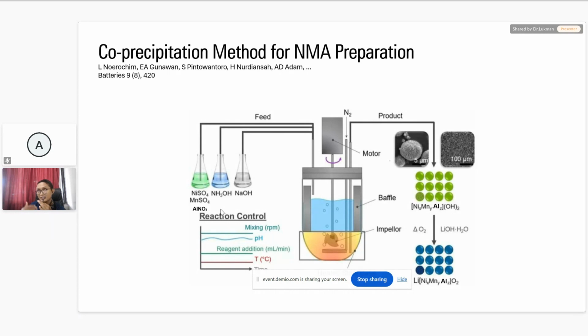So after we finish, around 10 or 12 hours, we filter this solution, and then we get the green color, yeah, and the green material will be transferred to the calcination process. For the calcination, we use an oxygen gas environment to improve the crystallinity of our powder. The calcination is usually at high temperature, around 800. In our experience, we use 800 degrees Celsius for around 10 or 15 hours.